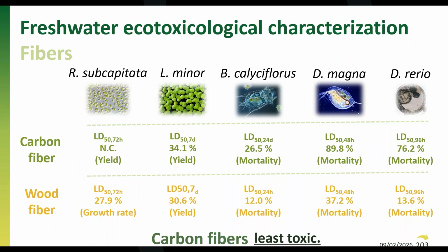Regarding the fibers, so the carbon fiber and wood fiber, here we have the same results, but here the unitary percentage, because remember that for this we tested the leachates, not the fibers directly dissolved in the test media. So here we also have the LD50s, here is a D because it's the dose, the dilution. And what we could see is that overall, both the carbon fiber and wood fiber induce some toxicity to almost all the tested aquatic organisms, except for the carbon fiber that did not induce a significant effect on the growth of the microalgae.